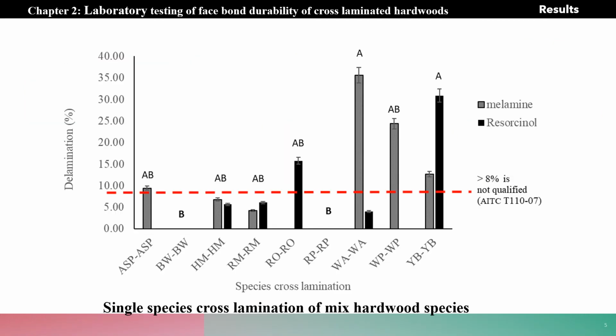So from the results of the delamination test according to the AITC, we realized that basswood and red pine did not show any delamination, though there was some delamination in yellow birch, white ash, and also some part of white pine, specifically with resorcinol.